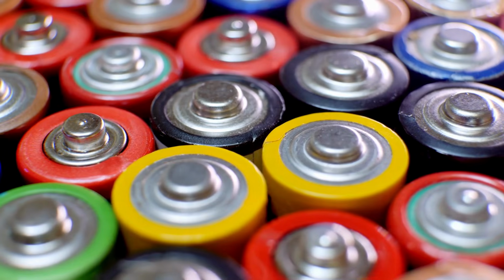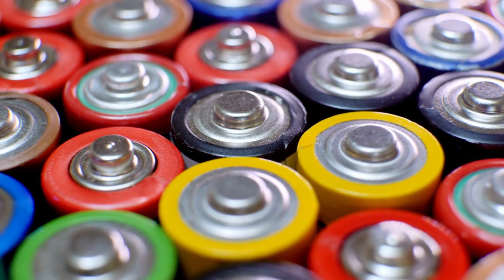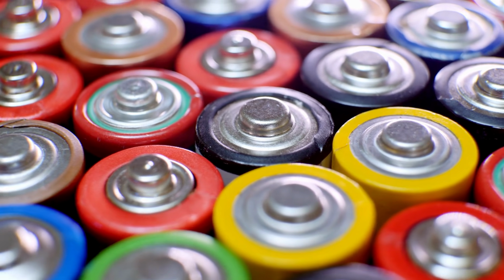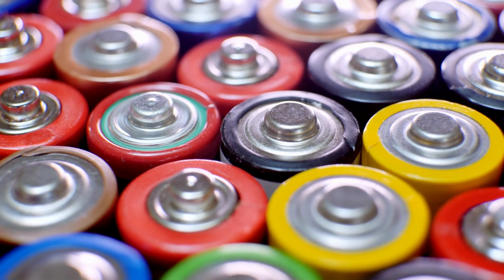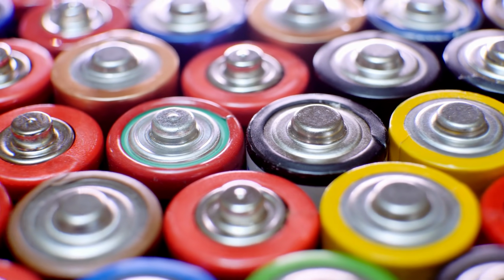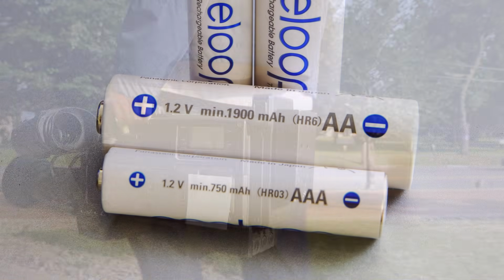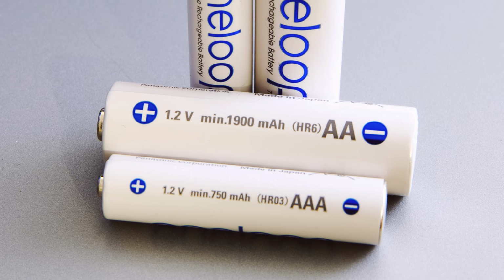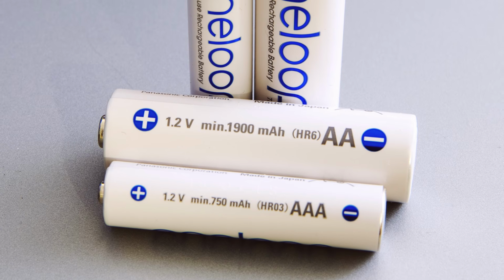Nickel metal hydride batteries did suffer from some drawbacks, such as having a higher self-discharge rate than lead-acid batteries, memory effect issues, and costs as high as 2 to 3 times more per kilowatt-hour when compared to lead-acid. Though with the emergence of inexpensive embedded microprocessors, advanced charging and battery monitor techniques could mitigate many of these chemistry issues. Nickel metal hydride became widely popular in the consumer space, quickly replacing nickel-cadmium and enabling a new surge in high-consumption mobile electronics. Ultra-low self-discharge variants would eventually be developed in 2005 for the consumer market, further increasing their appeal.